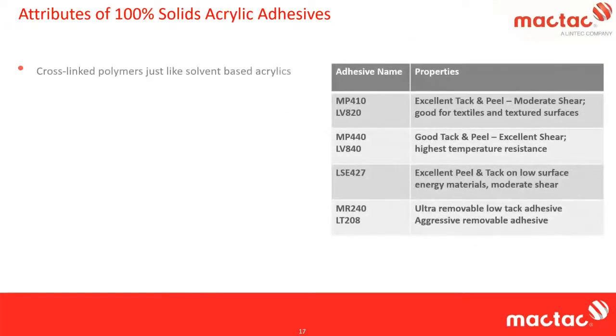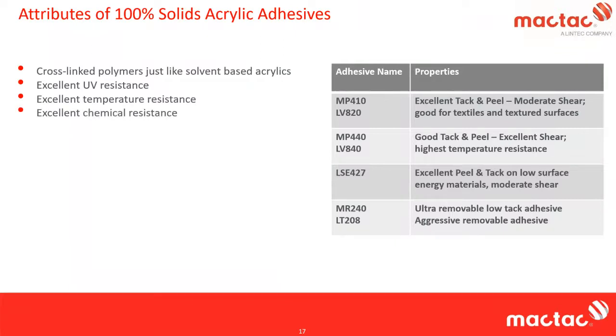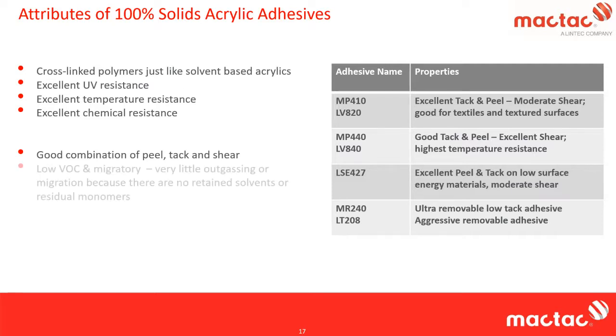When we talk about acrylic adhesives, they have very good UV resistance, and they are cross-linked polymers, just as 100% solids acrylics are similar to solvent-based products. They have excellent UV resistance, excellent temperature resistance, and very good chemical resistance, really pretty much across the board. And they give you a good combination of all of the properties that you're looking for: peel, tack, and shear. They also exhibit low VOC and migratory properties. So they have very little outgassing or migration because there are no retained solvents or residual monomers in 100% solids acrylic adhesives.